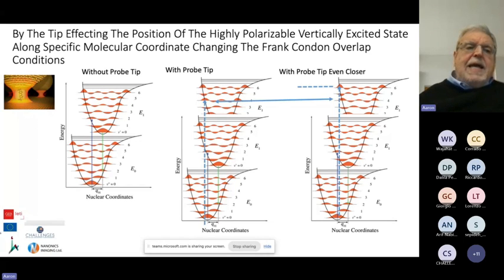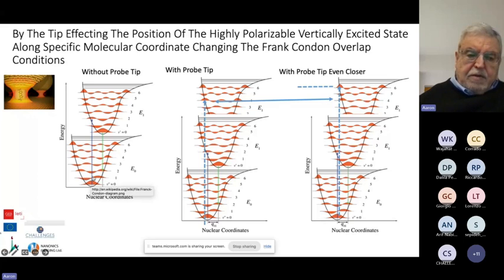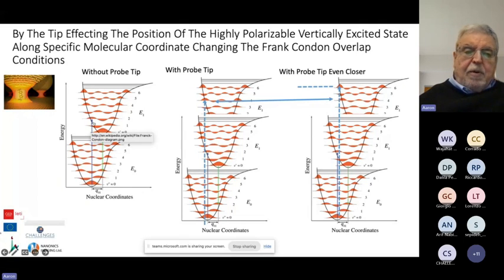So you must understand where Raman scattering comes from. Raman scattering comes from the overlap between the ground state and the excited virtual state. This is a virtual state that only exists when the photon is there, okay? So without the probe, the virtual state is here, and this is certain energy here, okay? And now you bring the probe tip to the sample, you can in fact shift the virtual state, and now the distance between the ground state and the virtual state is larger than what it is without the probe, and therefore the absorption has changed.